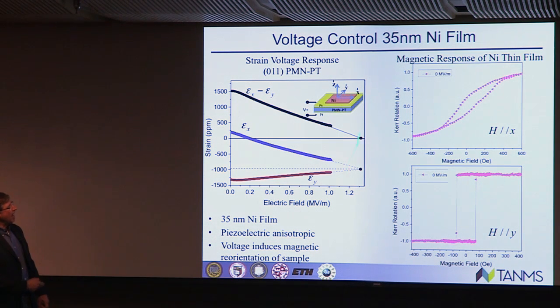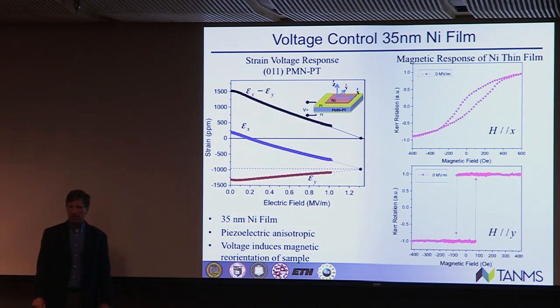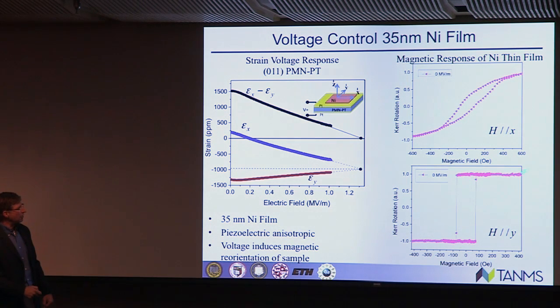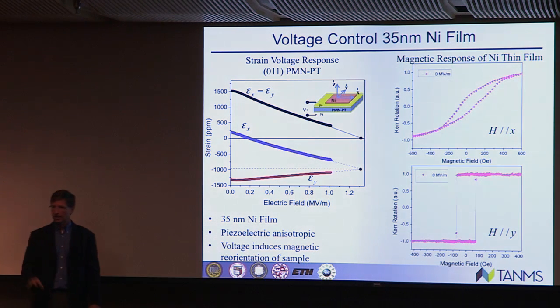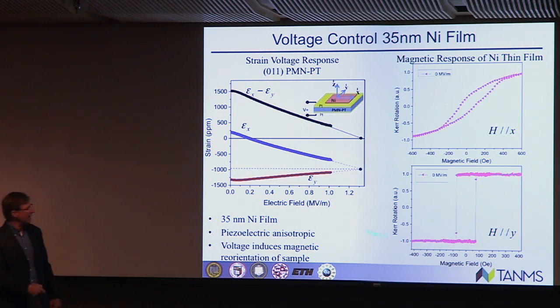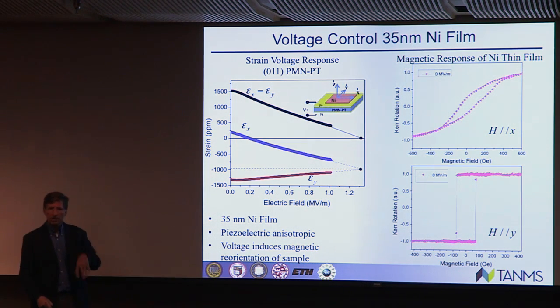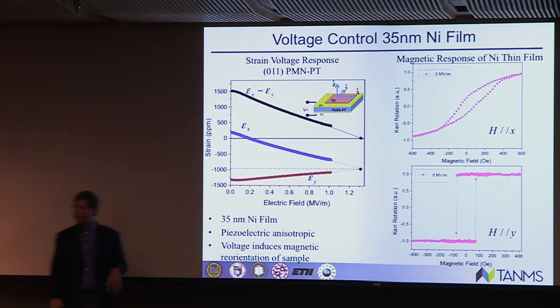So over here you have the magnetic response of our thin film. That's just one film. But we're going to look at the response along the X direction and along the Y direction. Now you may not look at magnetic curves that much, but you'll notice there's a difference between those two curves. And what you see is as you take the magnetic field off here, you actually have a really high remanence, where over here you have virtually no remanence. So what you're supposed to take from this is down here you have an easy axis, up here you have a hard axis. Now what we're going to do is walk through and apply voltages.